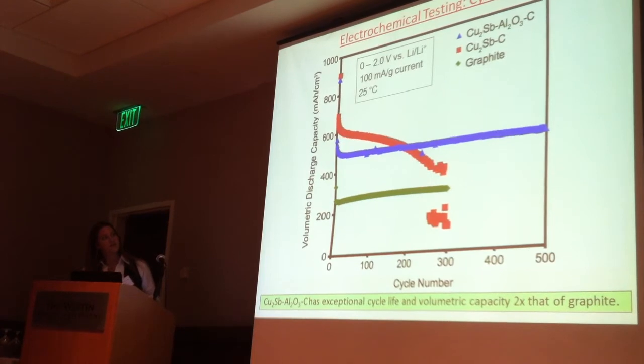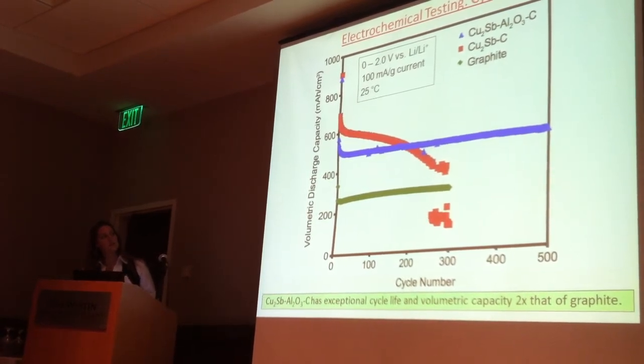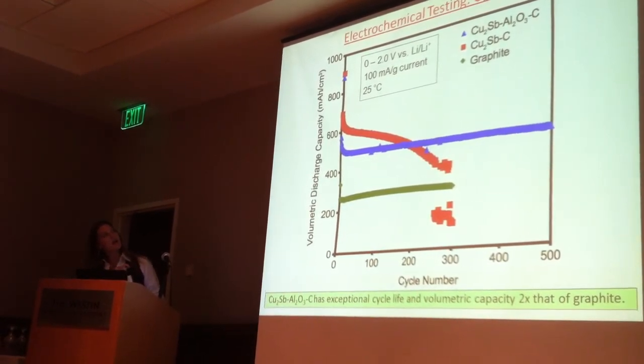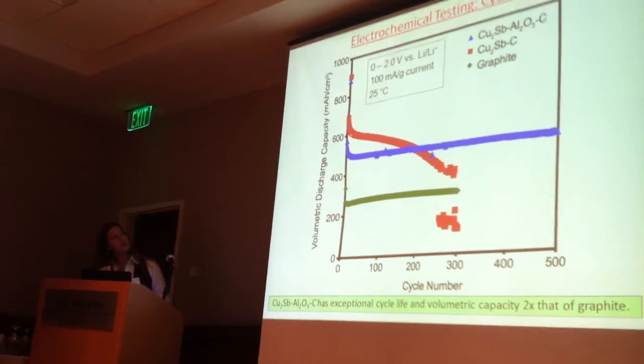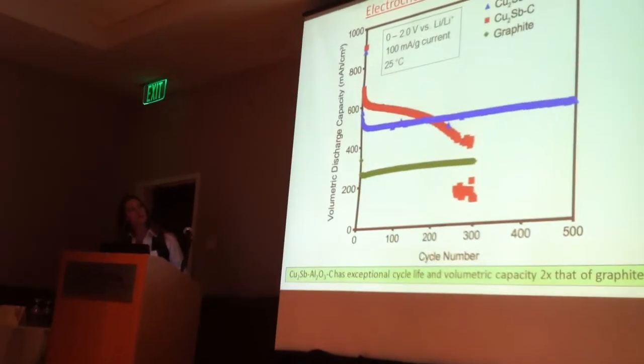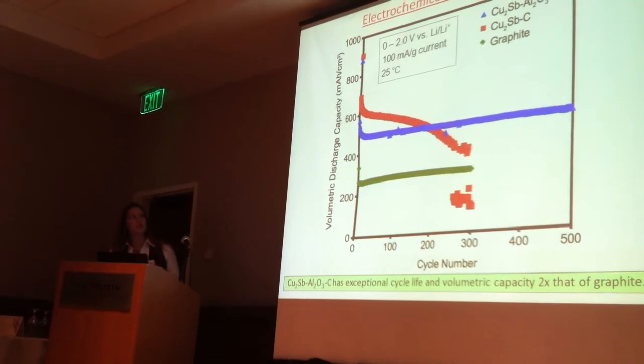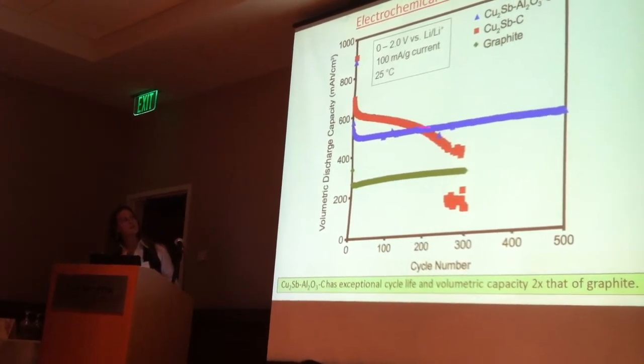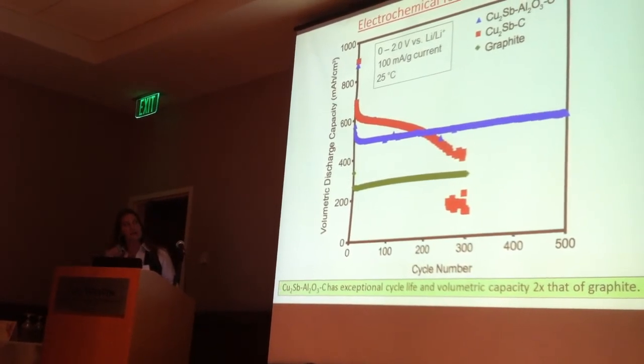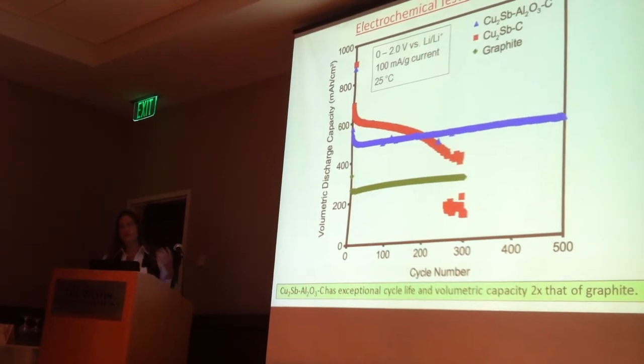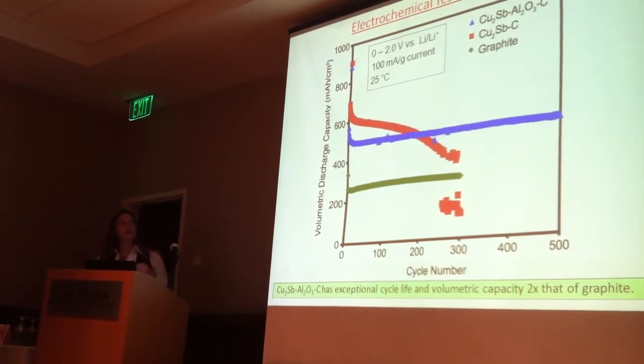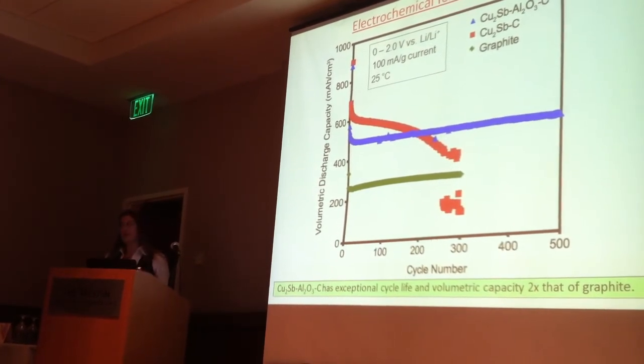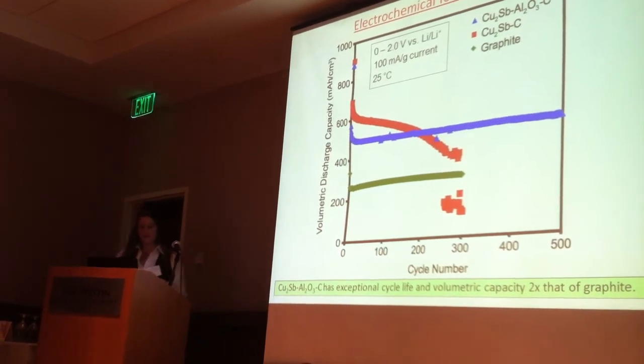This is graphite, the green line is graphite, that's commercial graphite. And you also can see that when you compare this red line, which is Cu2Sb, C of a similar particle size, to Cu2Sb, aluminum oxide, and carbon, there's a significant improvement. Aluminum oxide is having a big impact on the cycle performance for this material.